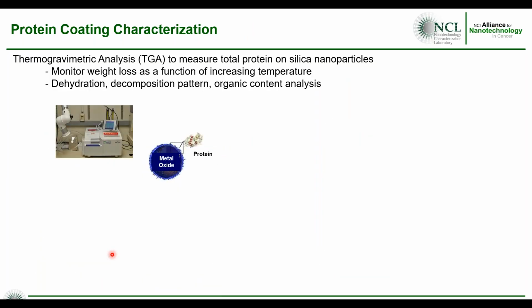Switching over to metallic nanoparticles, we want to look at protein loading. This is obviously important to know how much protein you have loaded on a metal oxide in this case. For this, we're using thermogravimetric analysis, or TGA. For those of you who are not familiar with TGA, essentially I will say TGA is basically taking a balance and then putting it in an oven. Turn the oven on, and you're basically burning off the organic, and the weight will decrease as a function of temperature.